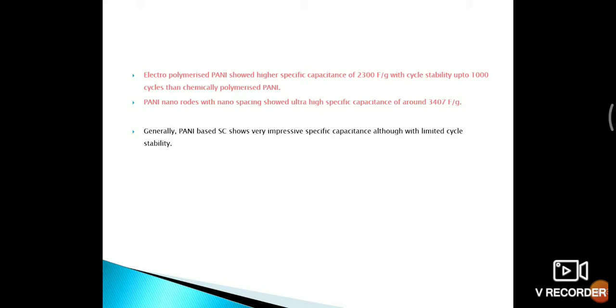The electropolymerized polyaniline showed higher specific capacitance of 2300 farad per gram with cycle stability up to 1000 cycles than chemically polymerized polyaniline. Polyaniline nanorods with a nano spacing showed ultra high specific capacitance of around 3407 farad per gram. Generally, polyaniline based supercapacitors show very impressive specific capacitance, although with a limited cycle stability.